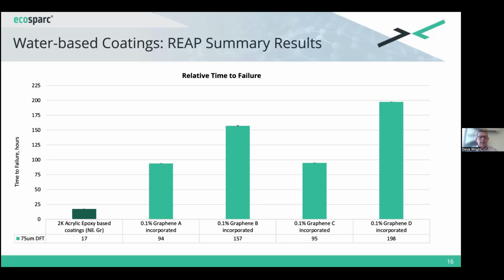And then a few months ago, better part of a year ago now, 2-pack acrylic epoxy coating. We put some grades of graphene into it up against a standard via REAP testing, R-E-A-P, so it's an accelerated test. And from that, we got some excellent results. We can pass out the reference material and the reference notes according to this. So we got significant improvements at 0.1% of graphene in there.